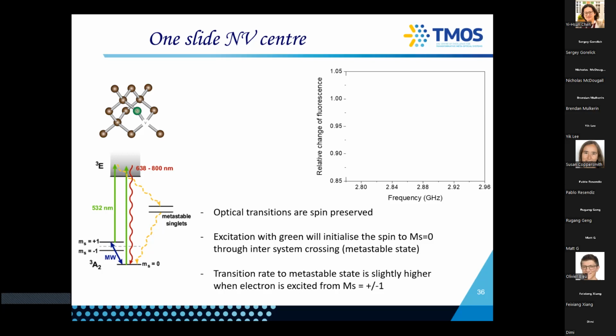One is that you can control the 0 to ±1 with the microwave, and two is the transition rate for your spin mixing, and the direct emission has a different rate. So one is 100 nanoseconds, the other is 10. And what it will give you is that if you apply exactly the microwave transition, your luminescence will go down, because you will basically drive this through here, and then you would get a reduction in luminescence.